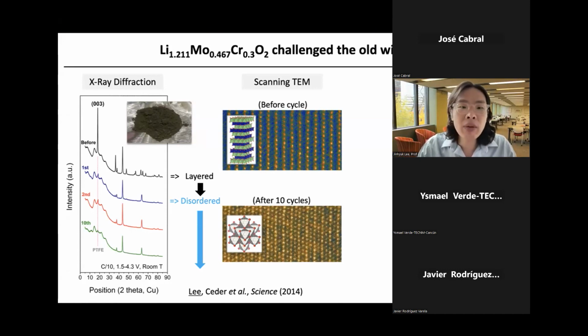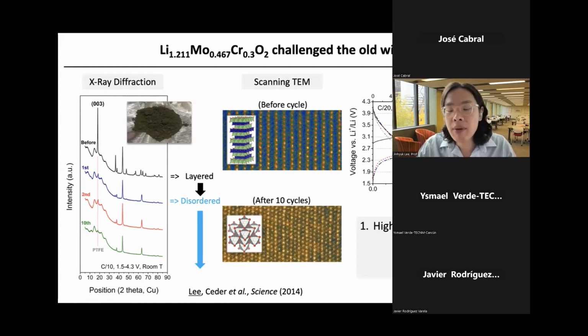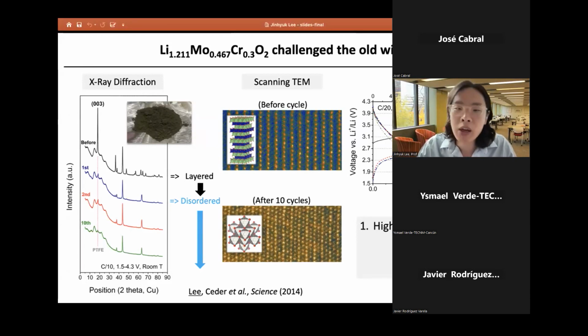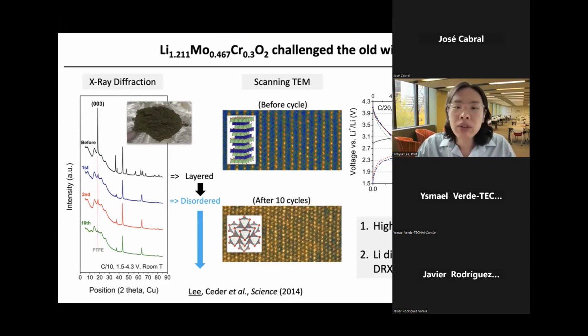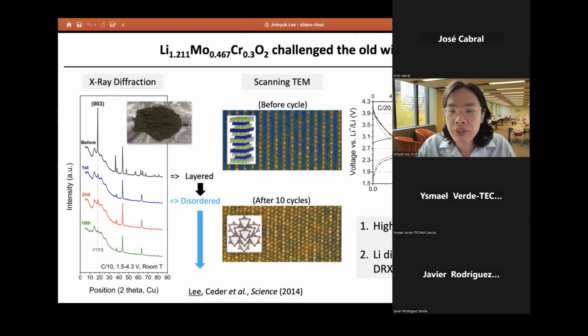But surprisingly, we found that this material can deliver very high capacity, up to 260 milliampere hours per gram, cycling around 1 lithium per formula unit, which was remarkably high considering that typical well-layered lithium transition metal oxide cathodes such as lithium cobalt oxide deliver around 160 to 190 milliampere hours per gram. So what these results actually suggest is that, in fact, the disordered rocksalt materials can be interesting high-capacity cathode materials, and this means that the lithium diffusion in the disordered rocksalt structure can be fast under certain conditions that people did not realize before.